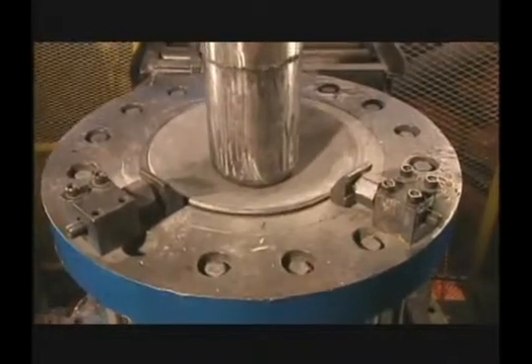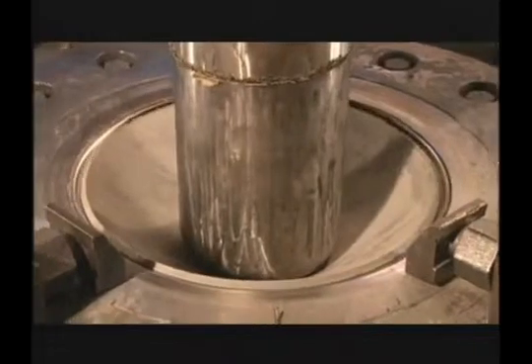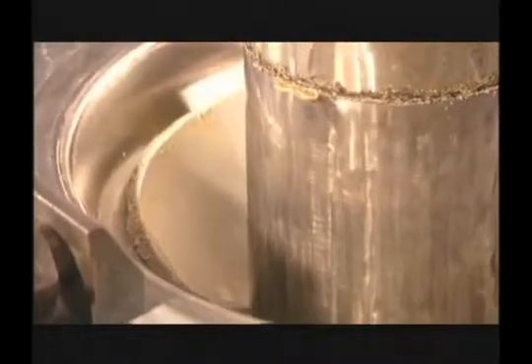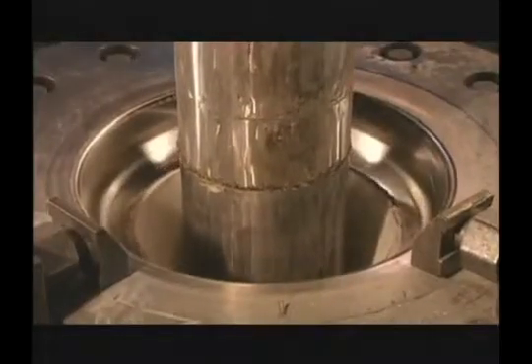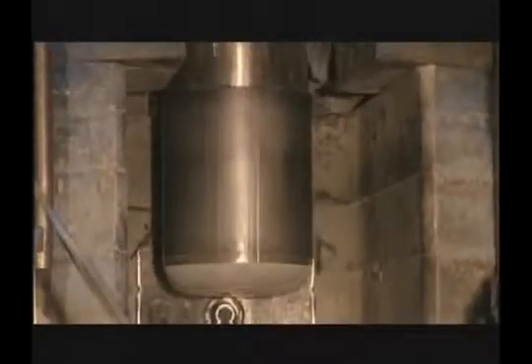This tooling is made from either high-grade tool steel, or it is sometimes inserted with carbide to provide better wear resistance. The first draw, or cupping press, utilizes up to 800 tons of force to complete the draw. After the cup exits the last ironing die, stripper jaws are engaged to remove the cup from the mandrel.